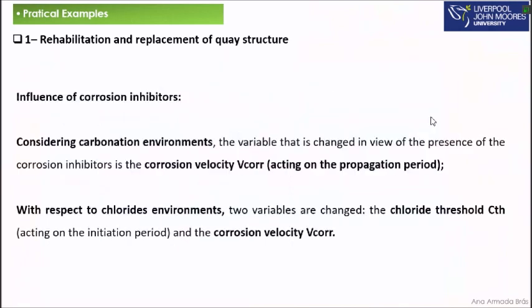So what is the role of corrosion inhibitors? Considering carbonation environments, the variable that is changed in view of the presence of corrosion inhibitors is the corrosion velocity. It tends to decrease. What about chloride environments? In chloride environments, the corrosion inhibitors can change the chloride thresholds, which is important to increase the initiation period. And they can also reduce the corrosion velocity, which will affect the propagation period also.